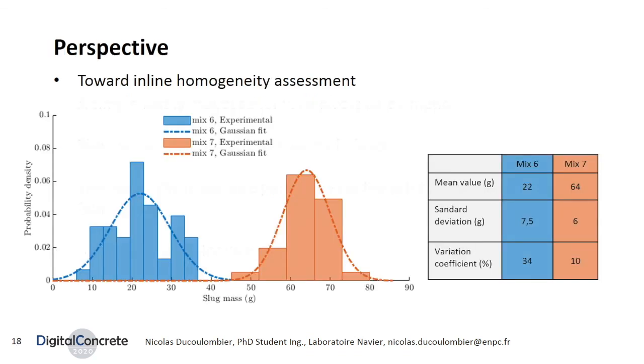The main perspective of this work is the statistical information provided by the automatic slug test. When plotting the probability density of the slug mass and fitting a normal distribution to the mixes 6 and 7 of the present study, significant differences concerning the standard deviation and variation coefficients can be noted between the two mixtures. To our mind, this coefficient of variation should give further information on the homogeneity of the material at the nozzle exit, which is particularly interesting when inline addition of additives such as accelerator, reinforcement, or aggregate is made during the printing. Upcoming work will tackle this issue.